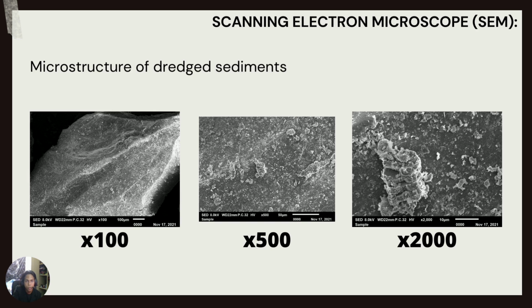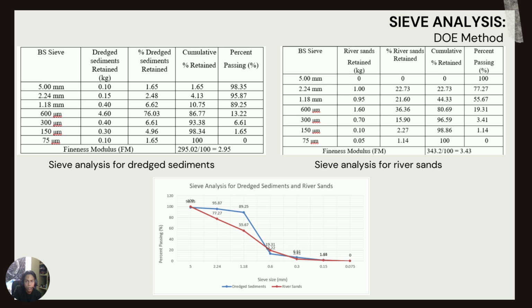Next, for the scanning electron microscope, the results obtained from the SEM with magnifications of 100, 500, and 2000 are shown in the figure. The material texture was observed, and the dredged sediments can be seen with a smooth and rounded surface texture. Next, for sieve analysis, the fineness modulus (FM) value was obtained from the cumulative percentage retained. The dredged sediments, at 2.95, were classified as medium sand, while the river sand, at 3.43, was classified as coarse sand. The graph illustrates the fine aggregate size distribution comparison between dredged sediments and river sands in order to assess fine aggregate grading.